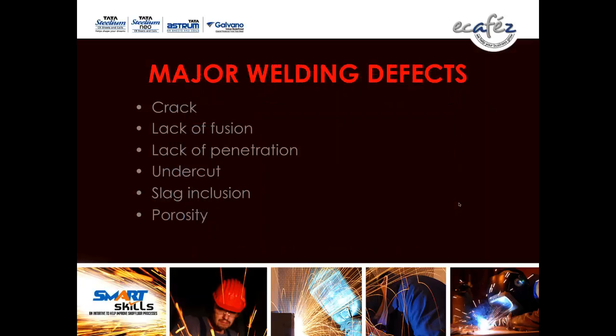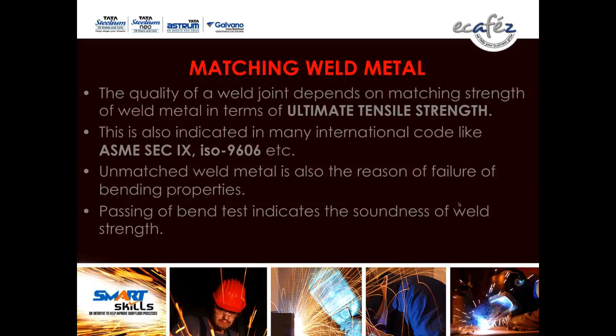Major welding defects, which I have quoted in good quality welding: good fusion and penetration, defect-free welding. The major welding defects are crack, lack of fusion, lack of penetration, undercut, slag inclusion and porosity. Matching the weld metal properties with the base metal, as I have intimated to you: the quality of a weld joint depends on the matching strength of weld metal in terms of ultimate tensile strength. This is also indicated in many international codes like ASME Section 9, ISO 9606, EN 287 Part 1, API 1104, wherever you go. Unmatched weld metal is also a reason of failure, the bending properties. Passing the bend test indicates the soundness of the weld.